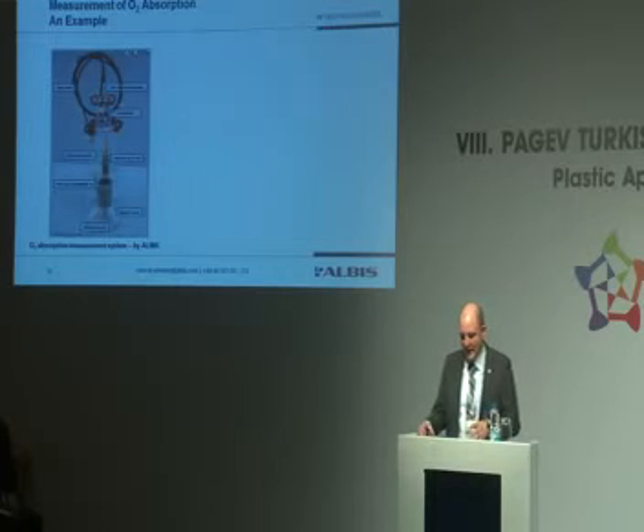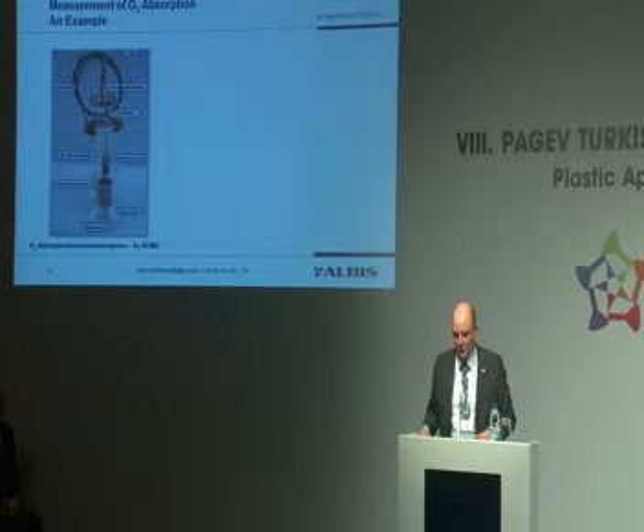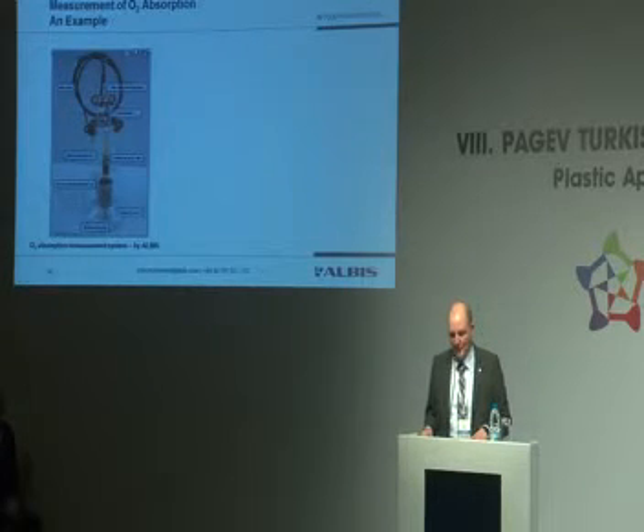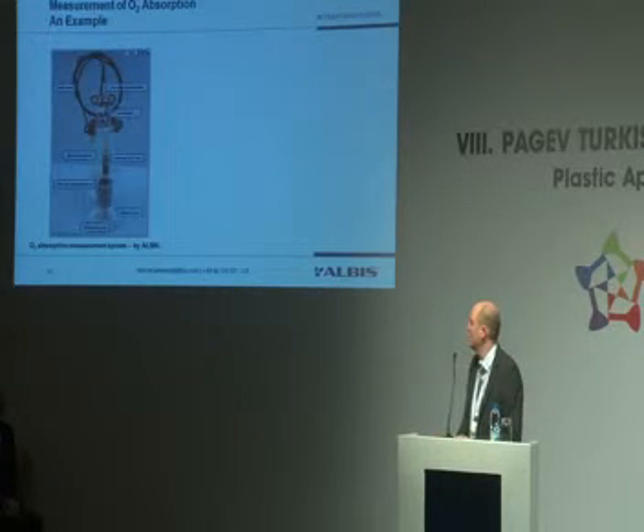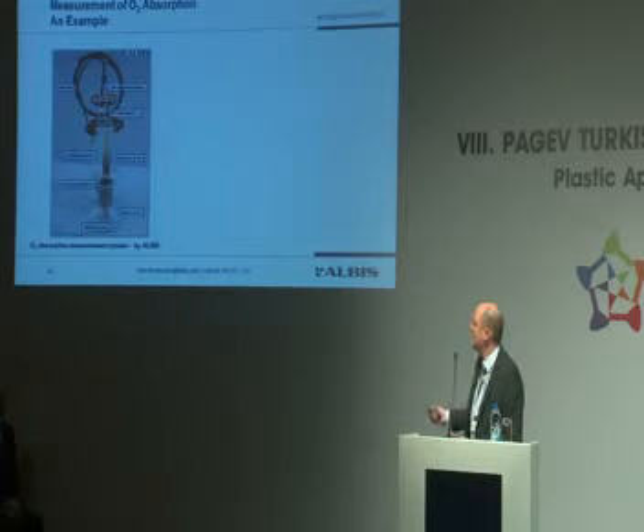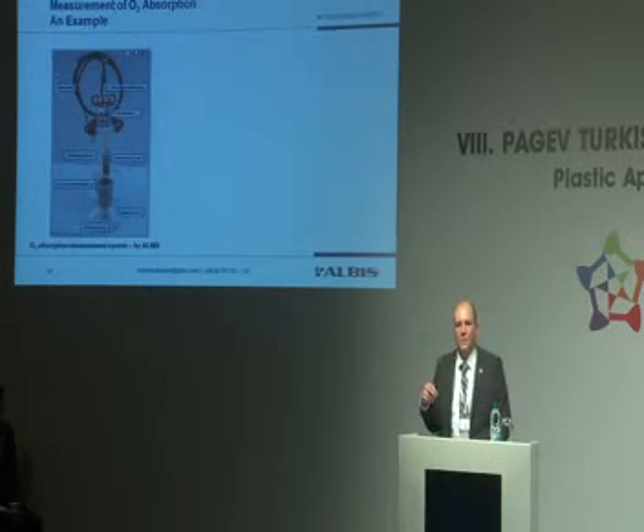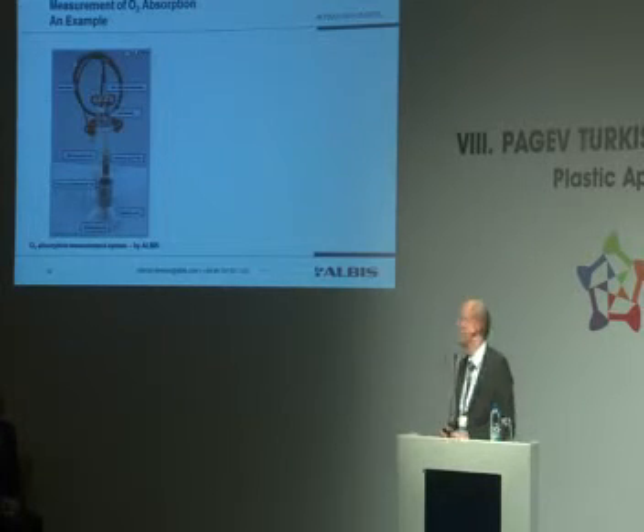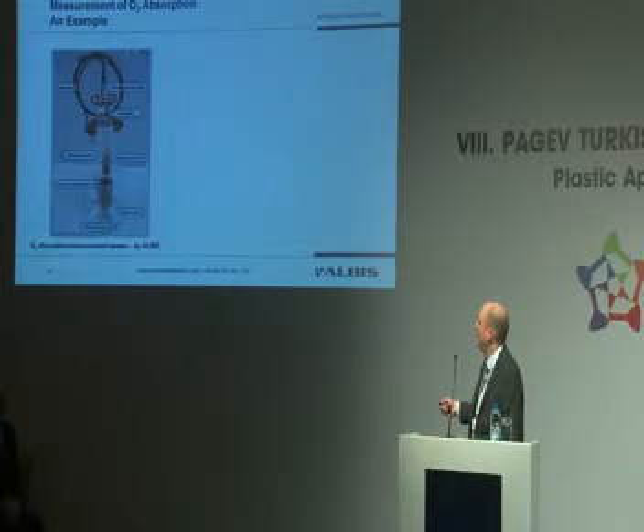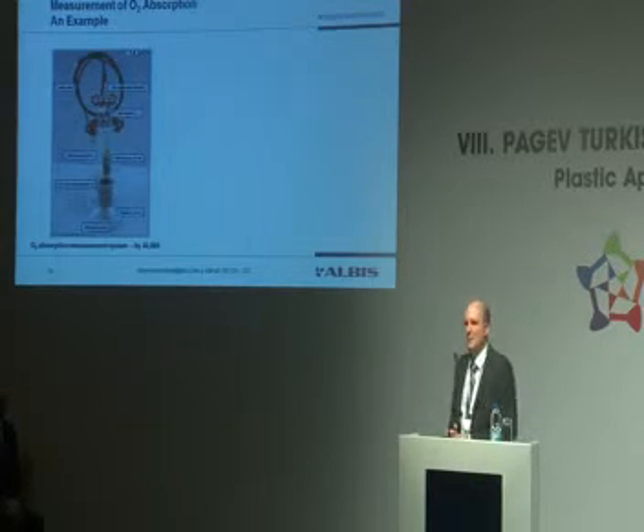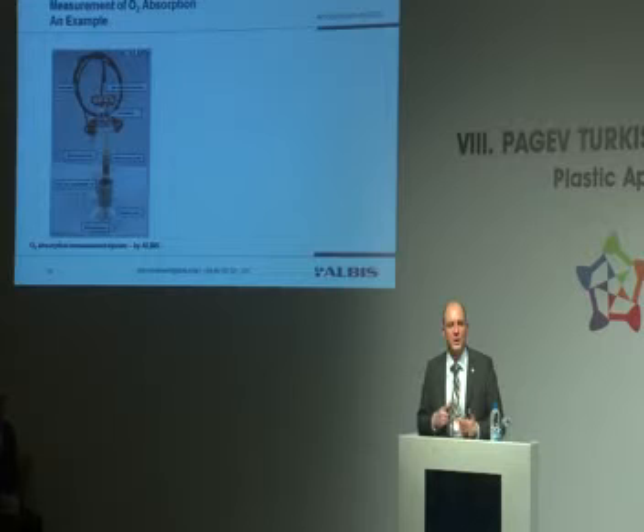Now, we had the principle. We have seen with some real applications that it is working. But also, we can scientifically measure what's happening. So we, as Albis, have developed a device to measure the oxygen absorption of film samples, which basically is straightforward. It's a glass vessel that can be closed airtight. On the bottom, we would fill some water in order to have enough humidity to activate the oxygen absorption. Then we put the sample inside here, and we have a sensor that constantly, meaning each minute, is measuring pressure, temperature, and humidity level inside the vessel.